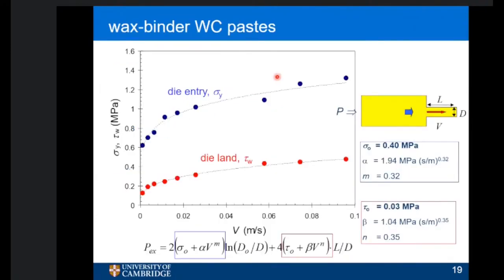Okay, and this is the sort of result you get from these wax binder tungsten carbide pastes. So these are the stresses in orders of megapascals. Just remember 1 megapascal is 10 bar. Okay, that is not a soft material. So the yield stress, the sigma y term, in terms of these velocities, is going from about 1/2 to well over 1 megapascal. So that means this stuff is pretty stiff. And your standard rheometers won't shift it. So that's another reason why we have to use ram extrusion to characterize it.